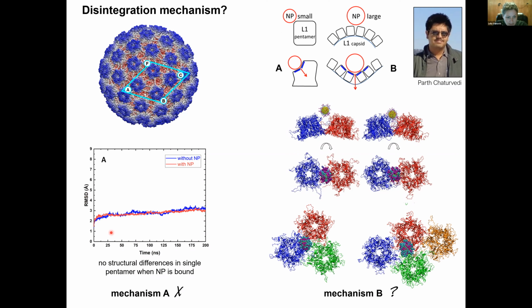And you can see that over time, this deviation of atoms looks pretty similar when you have the nanoparticle there or when you don't have it. So mechanism A is not the correct mechanism. That's not how these antiviral particles destroy the viruses. It's not on a single protein level. We then proceeded to examine mechanism B. If a nanoparticle binds to multiple viral proteins, is that leading to a distortion of the capsids? And is it going to break the capsids?